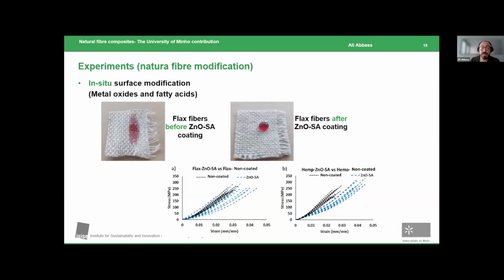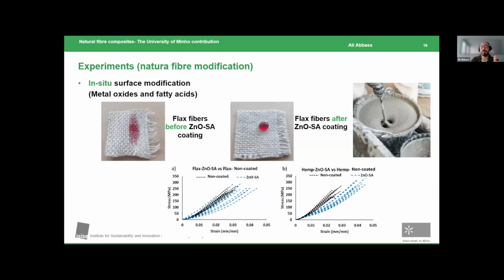So we've done the tensile characterization of this. Of course, we've done a lot of chemical, morphological, and elemental analysis of this, but I'm not going to show you all because then I'm not going to have time for other stuff. So here you would see the tensile behavior. We observed some sort of a decrease in the Young's modulus and increase in the strain. This is called plasticizing effect due to the alkalinity of the solution used. So after all, we observed that this might not be suitable for a 2D reinforcing kind of textile. It might be more suitable for short fiber composites in inorganic matrices.